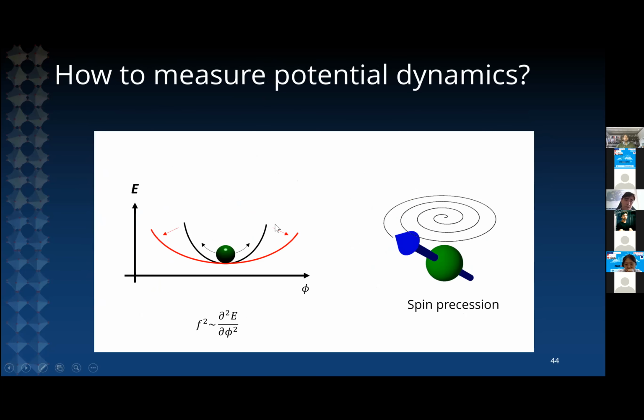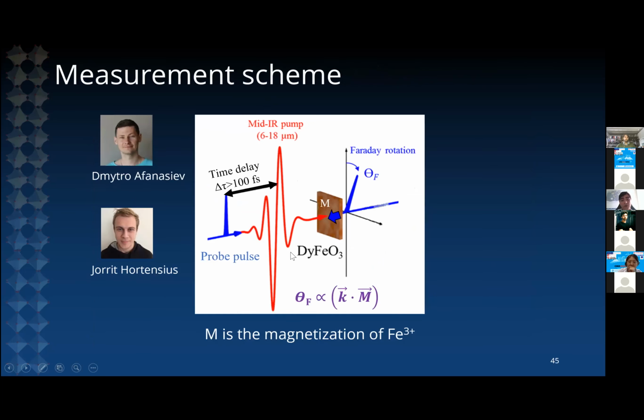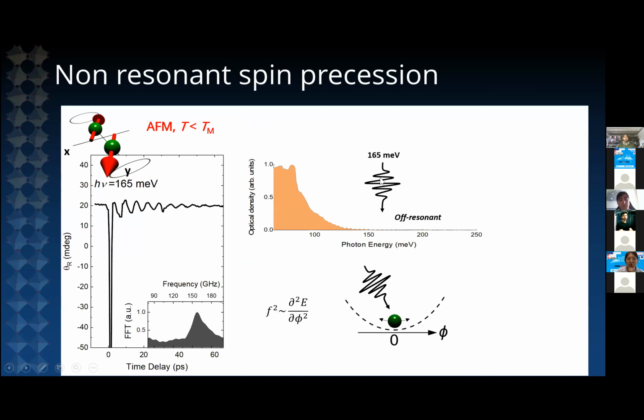So first of all, we measure the magnetic potential dynamics by monitoring the spin precession of our systems. So our measurement scheme is a time-resolved Kerr and Faraday rotation. So I will show mainly Faraday rotation measurements. So when we excite the system non-resonantly, we induce spin precessions, which matches very well the Raman data of this system.